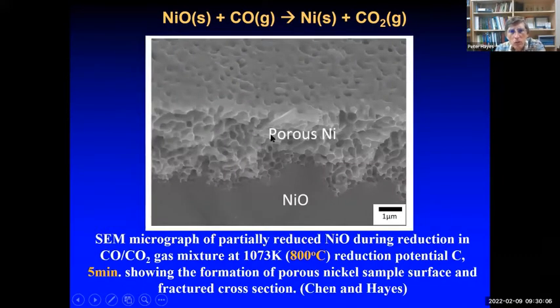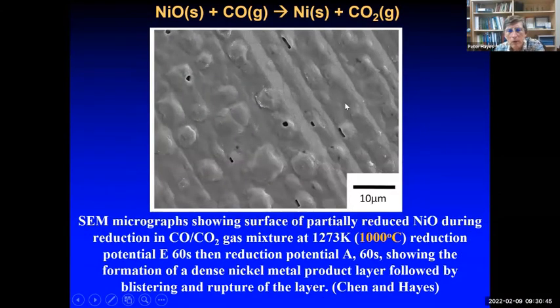If we change the gas condition, what happens is that we get that initial dense layer, and then it breaks down periodically, and we become porous again. So we call this a discontinuous growth. So this is the original surface, which was covered with dense nickel layer. Then those nickel layers broke down, and we had periodic formation of nickel layer and breakdown as we progress into the sample. Just to show you proof of that, this is at 1000 degrees centigrade at a very short time,